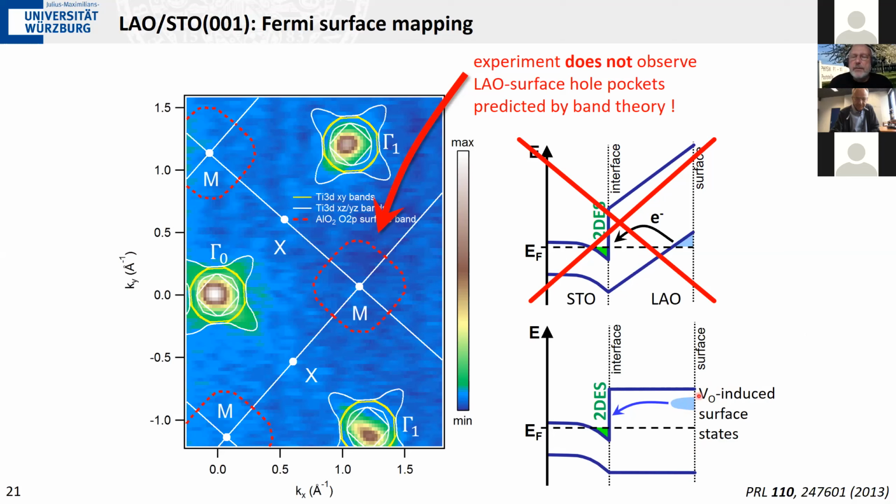They would pull off states from the valence band maximum and shift them all the way across the gap. They would end up above the Fermi level, so they would be empty states. And the depopulation of these states then leads to the filling of the 3d shell here.